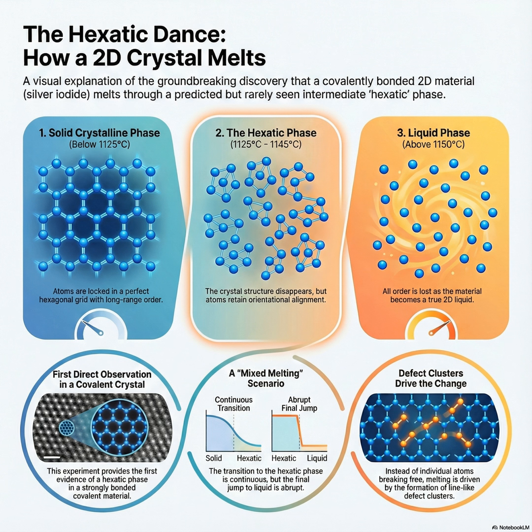So the verdict is in. The verdict is in. The team concluded that 2D silver iodide follows the mixed melting pathway. A smooth, continuous transition to the hexatic phase, followed by a sudden first-order transition into the fully liquid state. And they didn't stop there, right? They connected this mechanical proof back to the actual physical reason for it, the defects in the structure. In the original KTHNY theory, the melting is driven by the uniform creation of these isolated high-energy defects. They gradually weaken the lattice across the whole material, leading to a smooth transition.